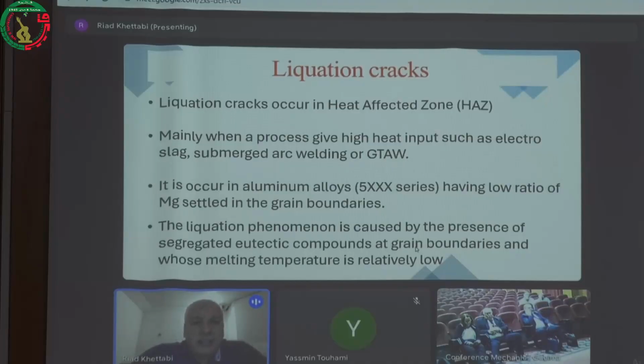So we are arriving at liquation cracks, or the liquation phenomenon. Liquation cracks occur in the heat-affected zone, HAZ, mainly when a process gives high heat input, such as electroslag welding, submerged arc welding, or other weld techniques such as gas tungsten arc welding. It occurs in aluminum alloys of the 5000 series having a low ratio of magnesium settled in the grain boundaries. The grain boundary is not in the grain structure, so just in the grain boundaries. We have this problem with magnesium and copper. So we present today just magnesium.